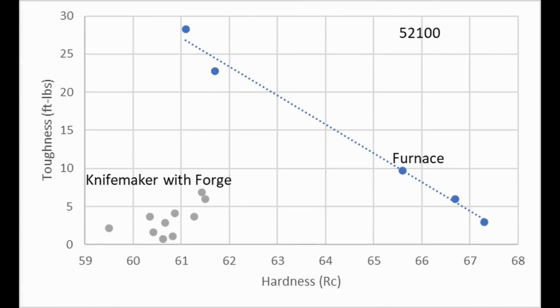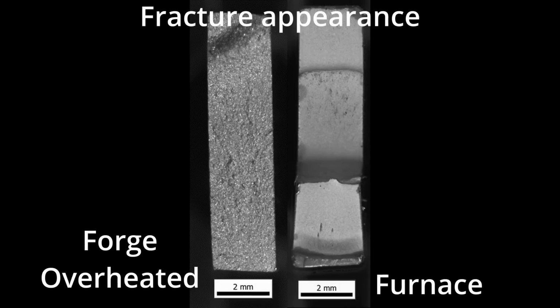Many knife makers have argued with me, said that they can get their heat treatments perfect every time, and about 3 of them have sent me steel for testing. And all 3 times the toughness was very poor with these toughness coupons that I tested. So I do not buy that knife makers can always hit it every time. Maybe some are better than others, maybe some are more consistent than others, but if you want to have dialed in consistent heat treatments, use a furnace, not a forge. And so this is a big problem, in my opinion, with custom knives out there.